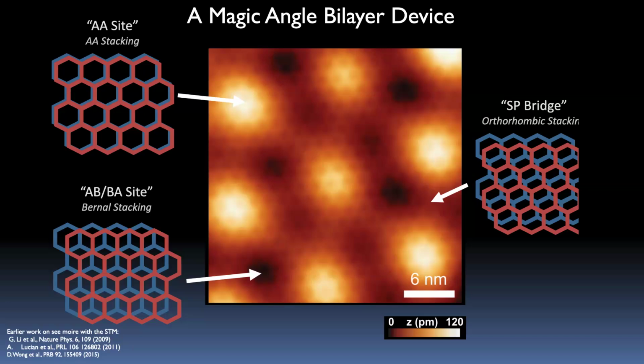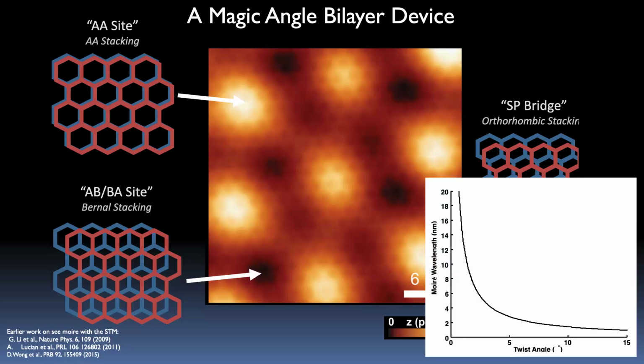What you see in the topography first is structural information. For example, you see different regions of stacking, which gives you AA and AB stacking of the 2 graphene layers. From the images directly, you can measure the twist angle, because the Moiré periodicity, which is the bright spots, tells you what the Moiré wavelength is, from which you can get the twist angle, provided the Moiré is not strained, which is a subject we will talk about a little bit as we go along.